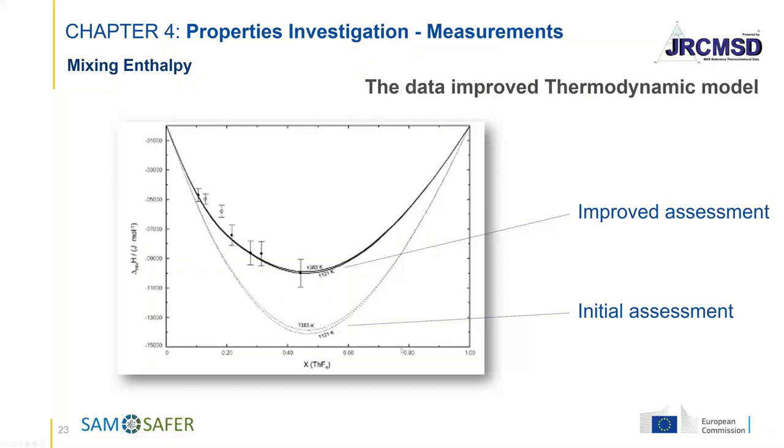And what is interesting to see here is that we have already modeled this lithium fluoride, thorium fluoride system in terms of thermodynamic description in the past, and we got a mixing enthalpy which corresponded to this curve, and for different temperatures. So of course it's unique for a temperature if it's temperature dependent. But with the data we measured, we had to improve it, and you see that the improvement is quite substantial. So it shows that even these mixing enthalpies are extremely important when you really want to improve the database, so that you can provide more and more reliable estimates.